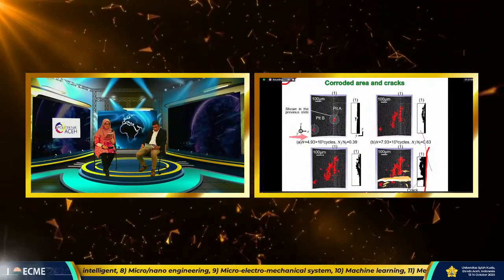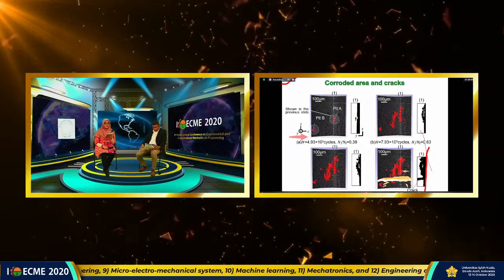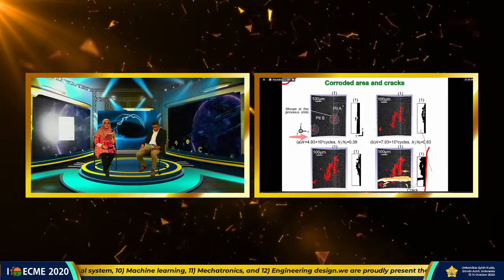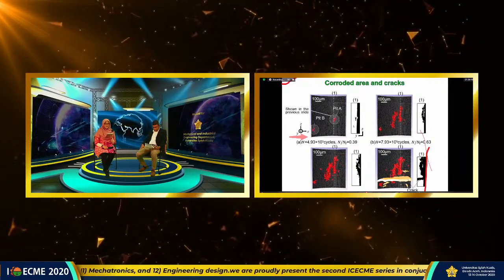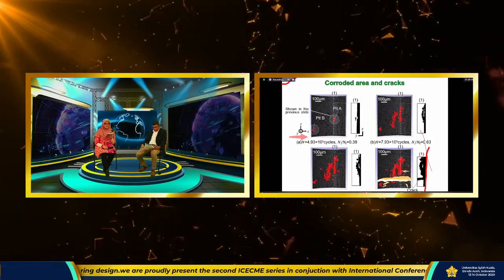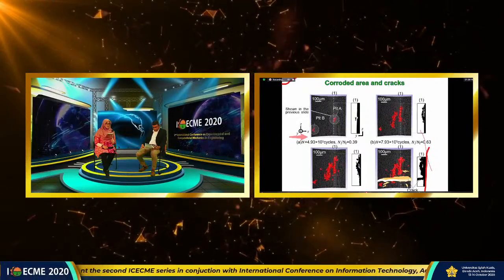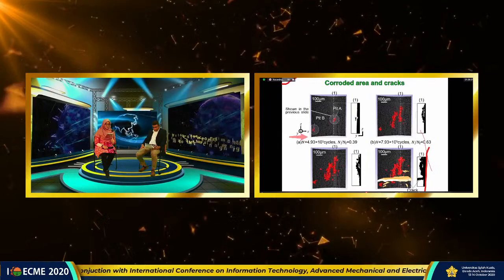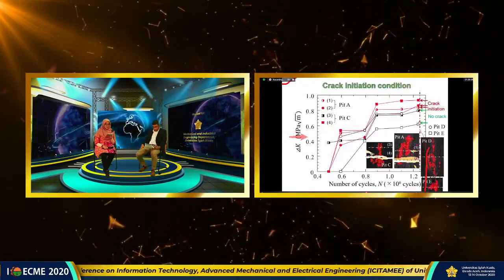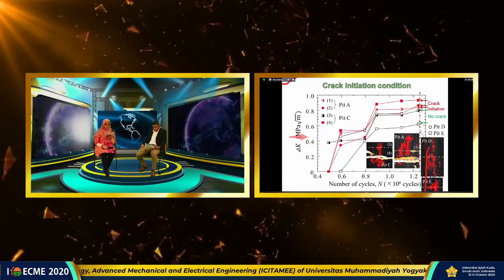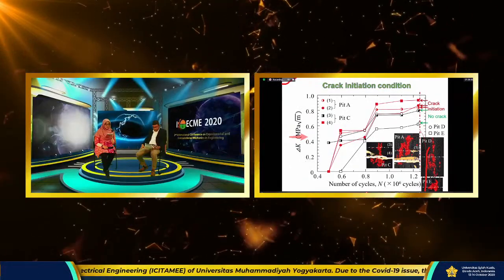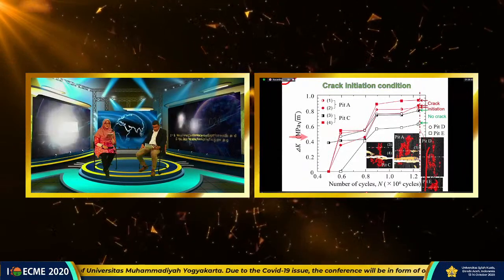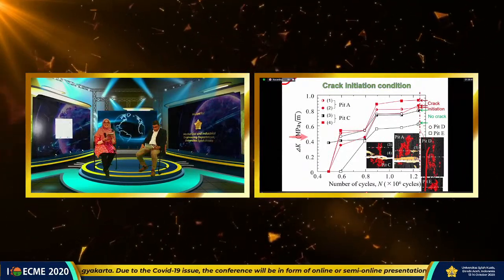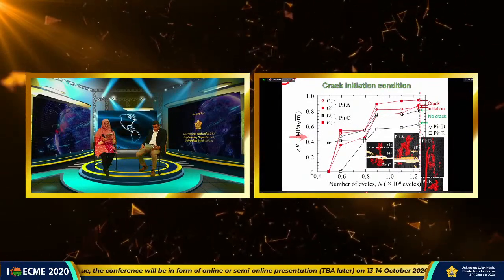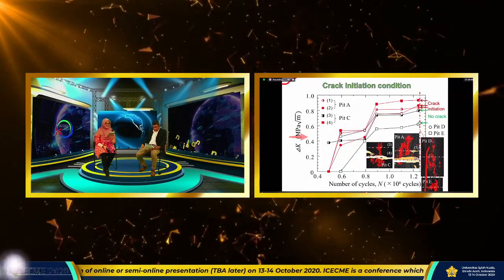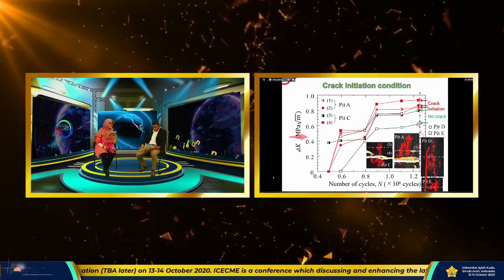This slide shows the corroded area and the cracks. In this figure, inclusion is not shown. So you can see the cracks initiate like this. This slide shows the change of stress intensity factor. In this case, I won't explain in detail, but it shows that the crack initiation occurs at a critical value of stress intensity factor of the corrosion pit.